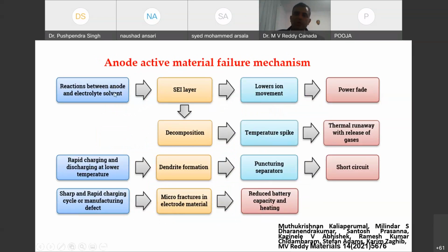Again, the material failure mechanisms, especially on the anode side: there is a reaction with solvent. Also, sometimes rapid charging causes dendrite growth and leads to short circuit. If it is manufacturing defects, you can also see reduced battery capacity, or if there is a reaction with solvent, you may see the solid electrolyte interface causing power fade. Also, due to decomposition, you may see thermal runaway, etc.